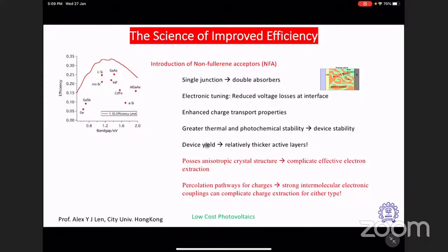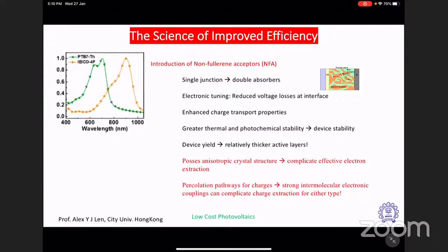Those are not the typical 70, 80 nanometer. I can go for a few hundreds of nanometer. And the moment I go for a few hundreds of nanometer, the processing over the large area becomes better, and device yield increases. That's one of the examples which I'll be showing you further in the coming slides. You have the donor PTB7TH and you have a non-fullerene acceptor now, not PCBM. There's some chemical structure which will be shown in the coming slide, but you get much more coverage.